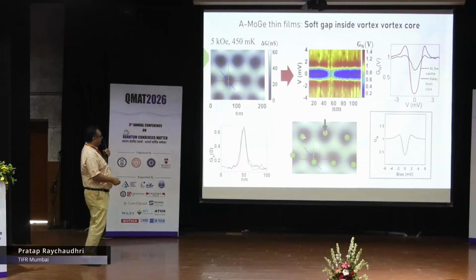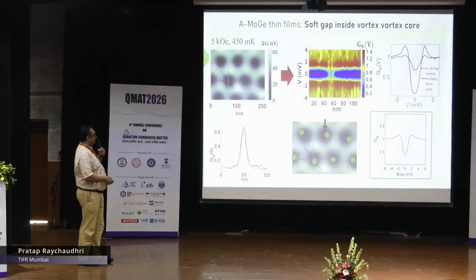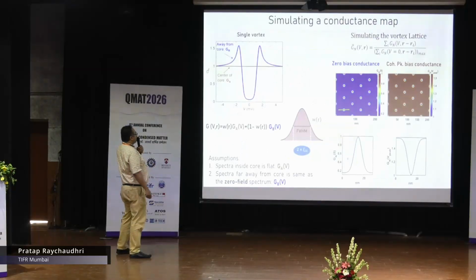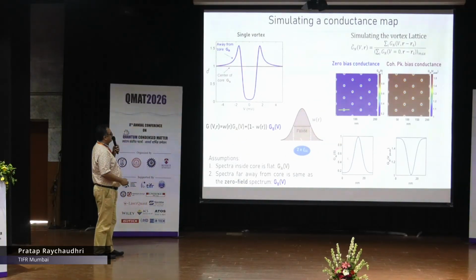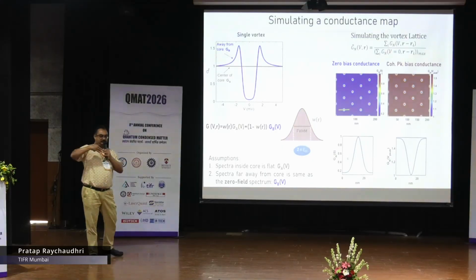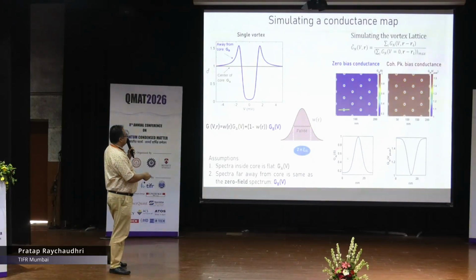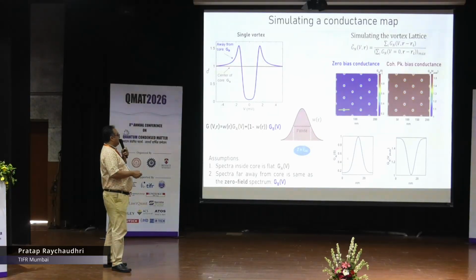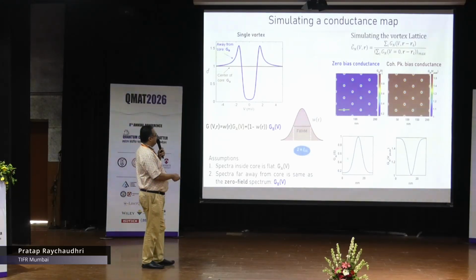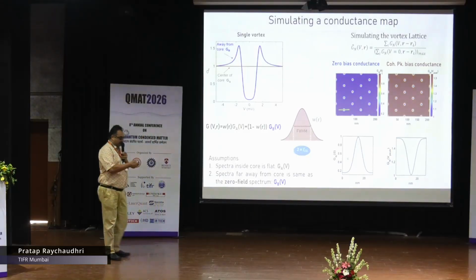Now for that I need to extract the amplitude of this vibration. The way we did it was to first simulate the conductance map for a static vortex lattice. These are all simulations of the conductance map at zero bias and at the coherence peak voltage. You can see here that at zero bias, at the vortex core, the normalized conductance goes to 1, and similarly the coherence peak also comes down to 1.